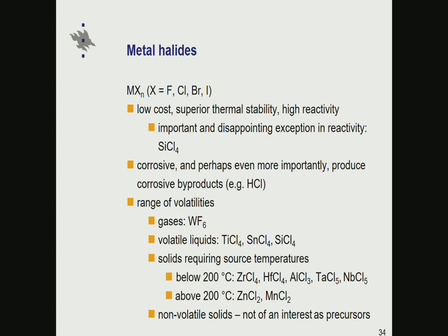They are starting materials. They show superior thermal stability. It's very difficult to decompose metal halides thermally. And in many cases they show high reactivity. One important disappointing exception here is silicon tetrachloride, but silicon is also otherwise quite disappointing in the ALD domain. But anyhow, these are corrosive. They are perhaps even more important: they produce HCl and other hydrogen halides as byproducts. One can live with these by proper choices in operating the reactors, choosing the materials there.